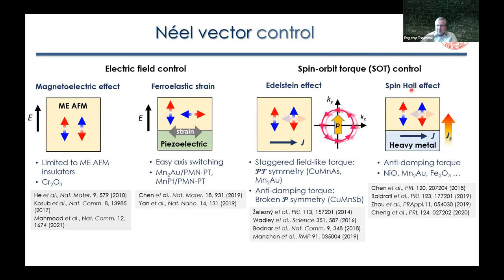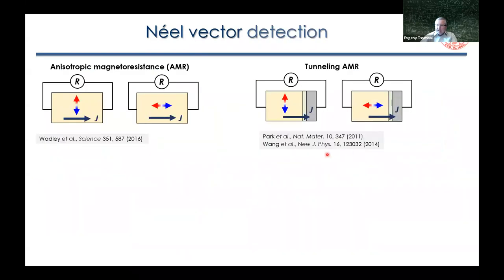Also, spin-Hall effect may be employed in the switching of antiferromagnets through anti-damping torque, and that has been shown again in a number of publications using a bilayer combining heavy metal and antiferromagnets. So in parallel, there has been quite substantial progress in detecting the Néel vector as well. So the most common way to detect the Néel vector is to use anisotropic magnetoresistance effect, or its analog, tunneling anisotropic magnetoresistance effect, where the resistance depends on alignment between the current density and antiferromagnetic order parameter.